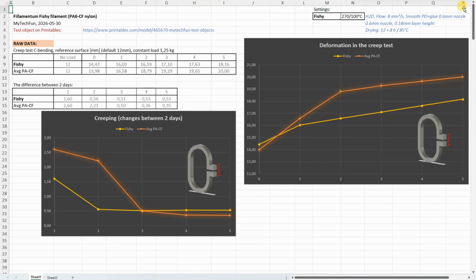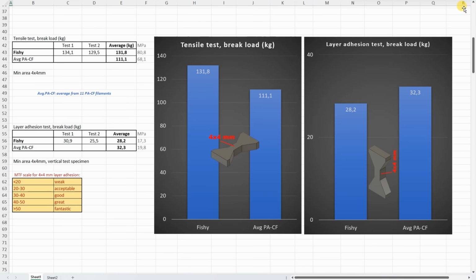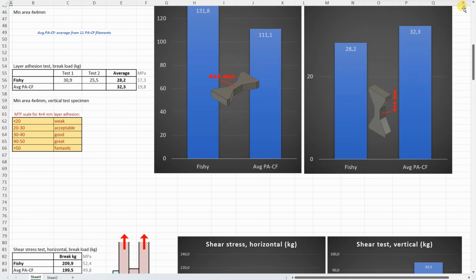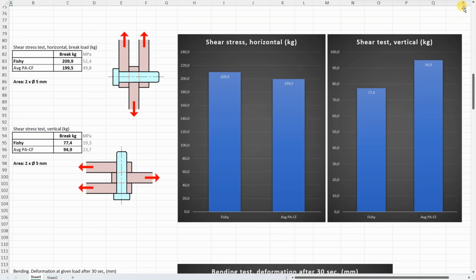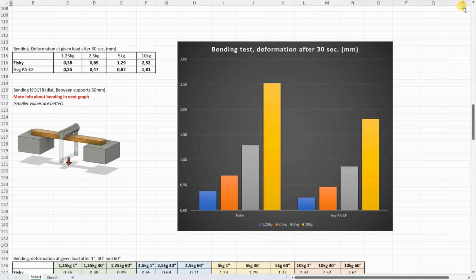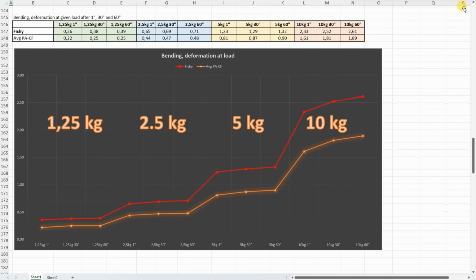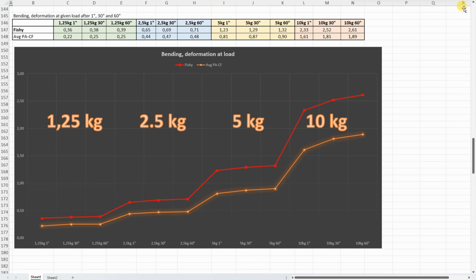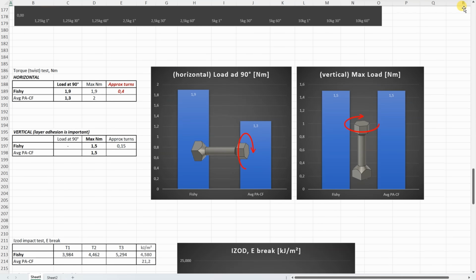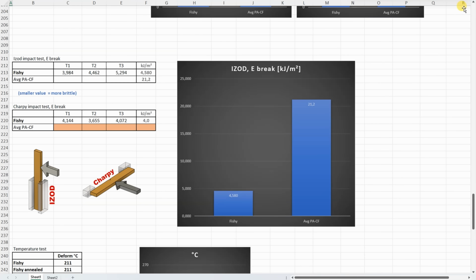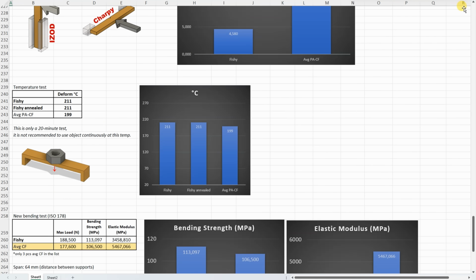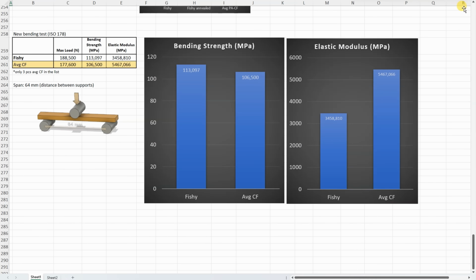All results one more time: creep test, tensile test and the layer adhesion, shear test, bending test, the deformation after 30 seconds, same bending test, but deformation under these loads after 1, 30 and 60 seconds. Shear test, horizontal, vertical. Impact test, Charpy and Izod. On a graph only the Izod is presented. Temperature test. And the second bending test.